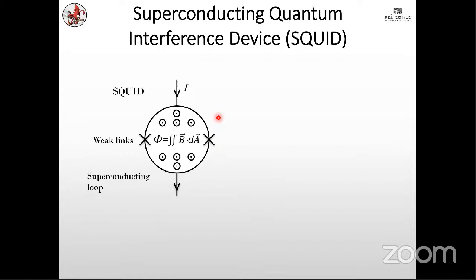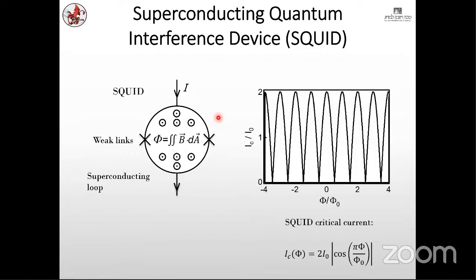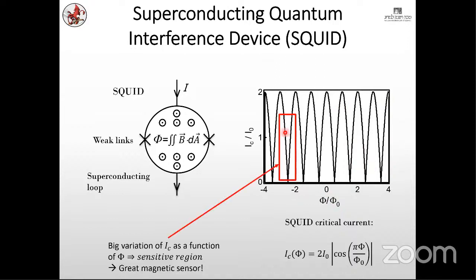so that the critical current there is much smaller than in the rest of the loop. And this results in a very interesting property, that is the critical current of this loop. Critical current is what I mentioned earlier. Critical current actually becomes periodic in the magnetic flux going through that loop. So if we apply a magnetic flux through such a loop, the critical current goes through these oscillations. And that itself is very interesting. But practically speaking, such oscillations immediately mean that we have a physical quantity which varies quite sharply with magnetic flux. And this variation can then be used as a sensor. And that is what a SQUID device does.